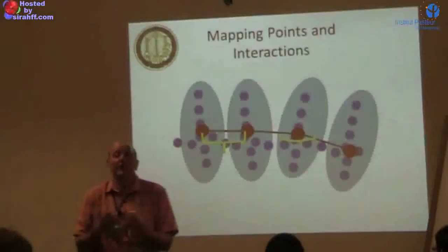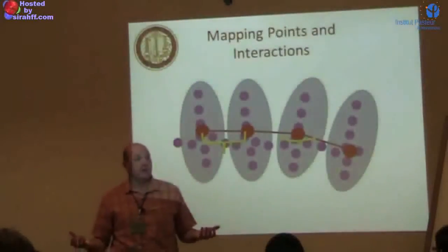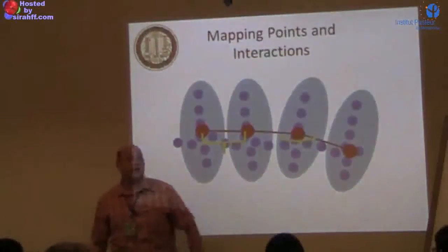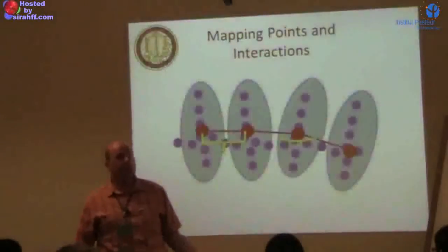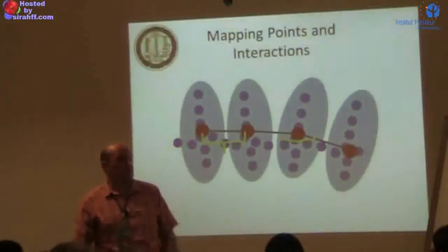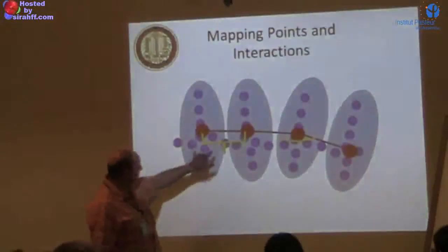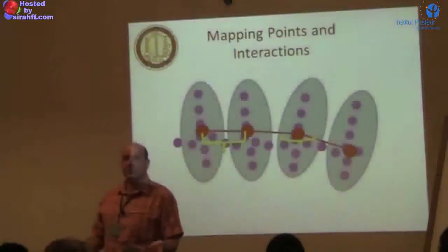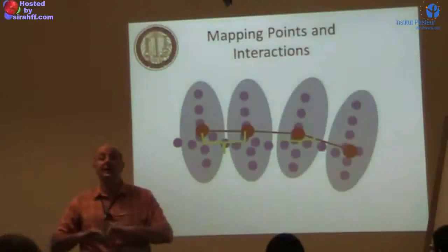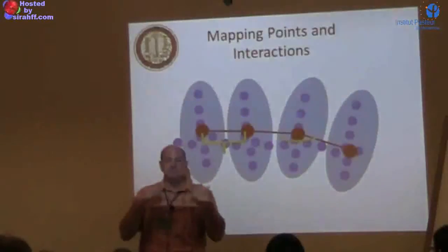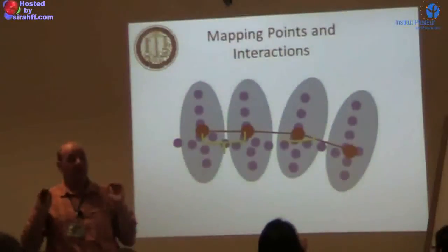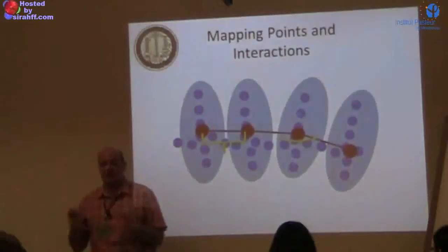If you would now go to what people call a real spring model, then you would really forget about all of that. You would have a spring and a Lennard-Jones sphere here, and then you get to the generic model with the fast polymer. But that polymer wouldn't know what the atomistic model is below it. What we want is a bond distribution, a bond angle distribution, as well as a non-bonded distribution, which represent kind of a mean field for the interaction. That's the fundamental idea. The point is that it cannot be a potential energy anymore.